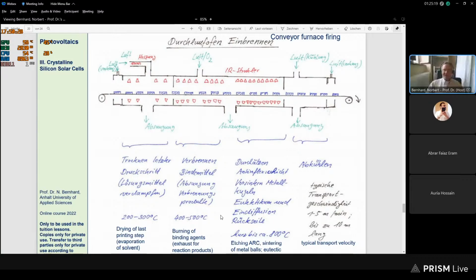And the last one, which is the most important one, runs up to 800 degrees centigrade. It's firstly the etching of the fingers through the anti-reflective coating. I said already, one has to etch through it because this is an insulating dielectric. And at the same time, in the paste, of course, the metal is in the form of flakes or balls. That means these flakes or balls are sintered together in this step. And at the back side, in addition, a silicon-aluminum eutectic is formed. And this eutectic finally makes the right contact on the back side.